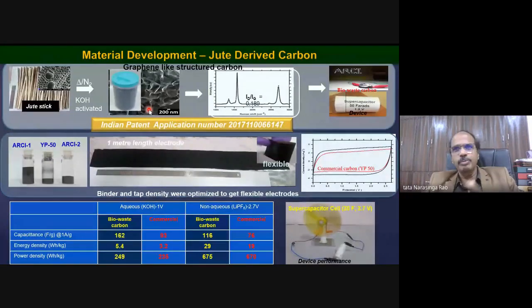And material development, again carbon. I should have carbon with huge specific surface area so that I can store a lot of charge. So we make jute-based carbon, which is graphene-like. You can see the 2D band of Raman, and then we make a supercapacitor out of that. See, in this cyclic voltammogram, the black one is the ARCI material, and the red one is YP50, a Japanese benchmark commercial carbon with high surface area used in Maxwell American supercapacitors. The area under the curve is the capacitance. We are better than even YP50, a commercial material.